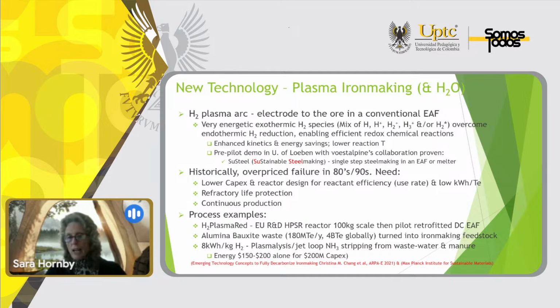Now, there are some processes out there. There's the hydrogen plasma reduction, which is European research and development. It's a reactor that's 100 kilogram scale. And if it works, it will then be pilot retrofitted to a direct current EAF furnace. There's an alumina bauxite, 180,000 ton a year plant turned into an iron making feedstock. And then, as I said earlier, this plasmalysis jet loop ammonia stripping from wastewater and manure is also a process that could potentially save the hydrogen world by producing hydrogen at 8 kilowatt hours per kilogram.